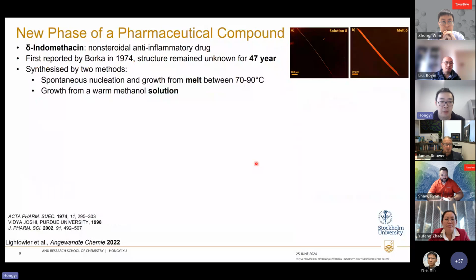Right, and the next example I want to show is discovering a new phase. This is indomethacin, a non-steroidal anti-inflammatory drug. For 47 years, the structure of this polymorph was unknown because single crystal growth was almost impossible. It's very difficult to grow a large crystal of this compound. But it has been reported that there are two ways to grow this crystal: one using a solution-based method, and one using the melt crystallization method.